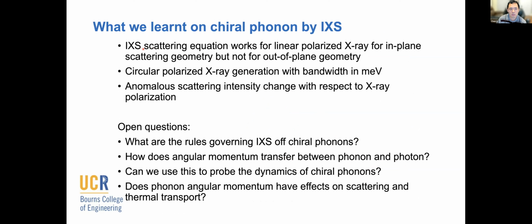The scattering formalism for the dynamic structure factor definitely works for linear polarized X-rays if we are looking at in-plane scattering geometry when we are working with chiral phonons. But once it's out of plane, the intensity doesn't agree anymore. And we are able to use circular polarized X-rays and to see that there's anomalous scattering intensity between different polarizations of the phonons. And it's actually possible to do such inelastic scattering with polarized X-rays with very narrow bandwidth.